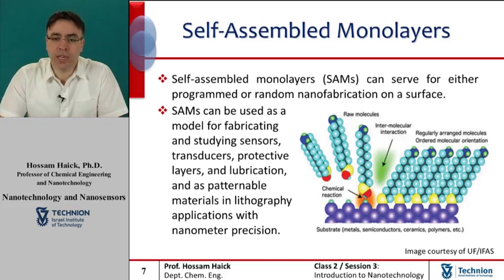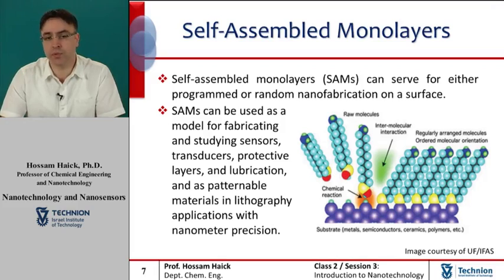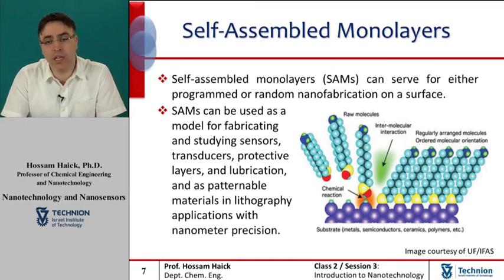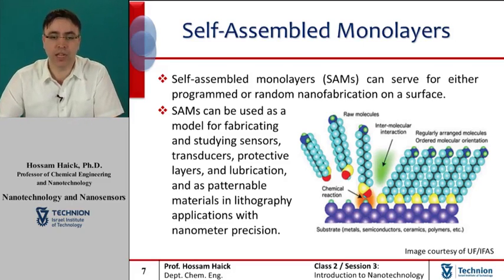Self-assembled monolayers are created by the chemisorption of head groups onto a substrate from either the vapor or liquid phase, followed by a slow organization of tail groups. Initially, at small molecular density on the surface, adsorbed molecules form either a disordered mass of molecules or an ordered two-dimensional lying-down phase, and at higher molecular coverage, over a period of minutes to hours, begin to form three-dimensional crystalline or semi-crystalline structures on the substrate surface.